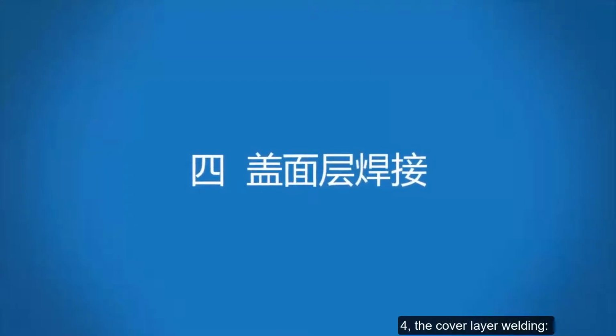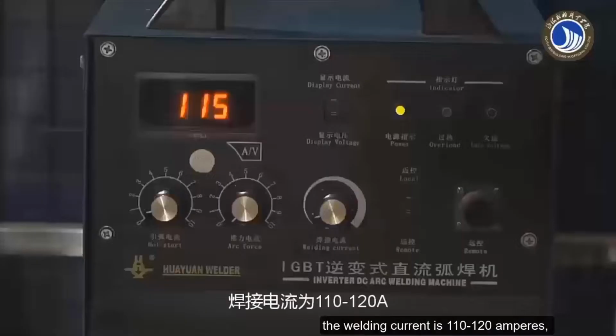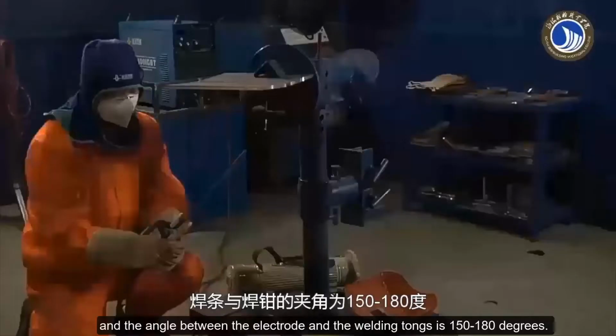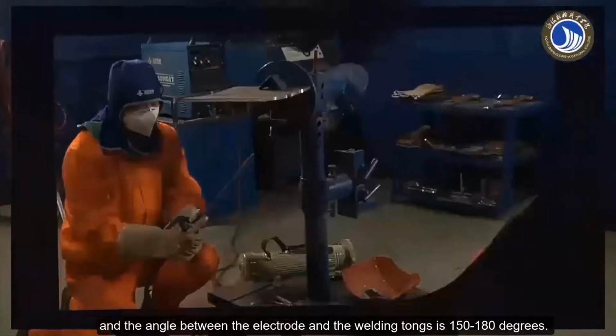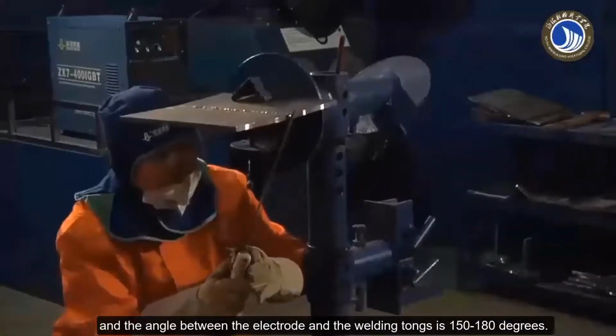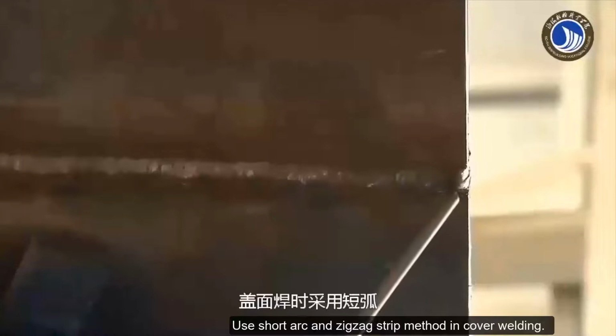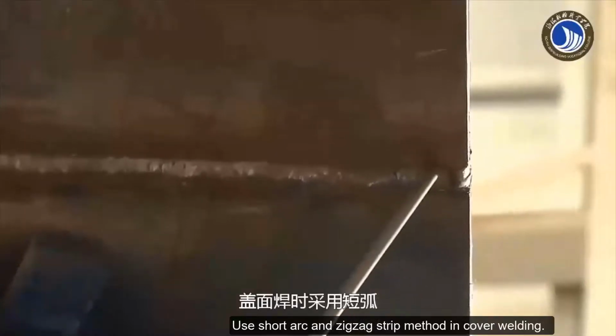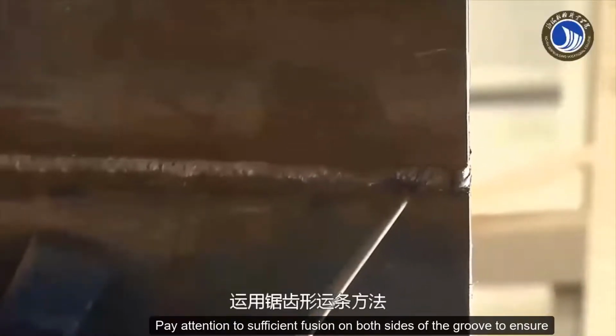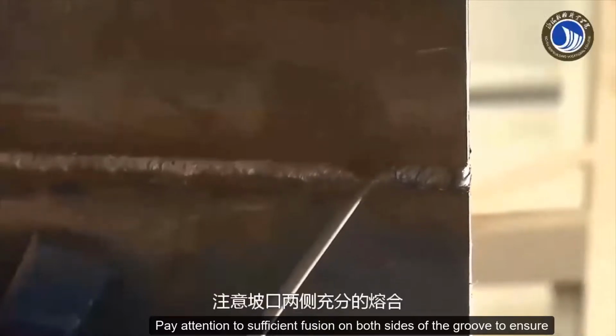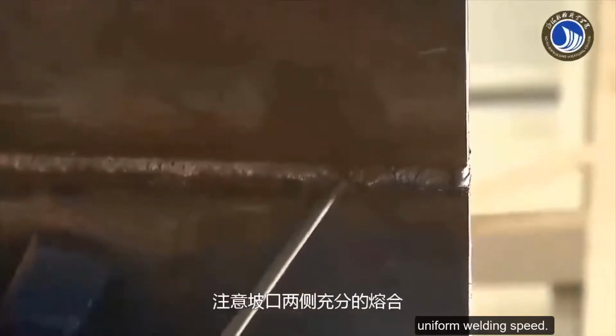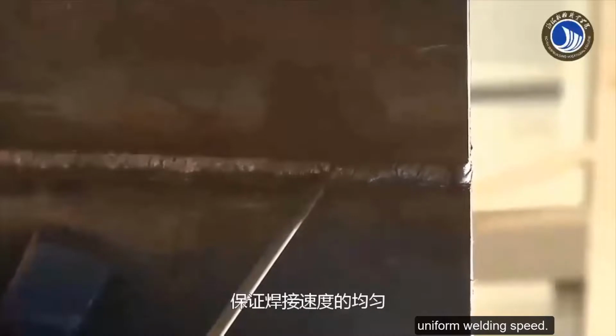4. The cover layer welding. The welding current is 110 to 120 amperes, and the angle between the electrode and the welding tongs is 150 to 180 degrees. Use the short arc and zigzag strip method in cover welding. Pay attention to sufficient fusion on both sides of the groove and ensure uniform welding speed.